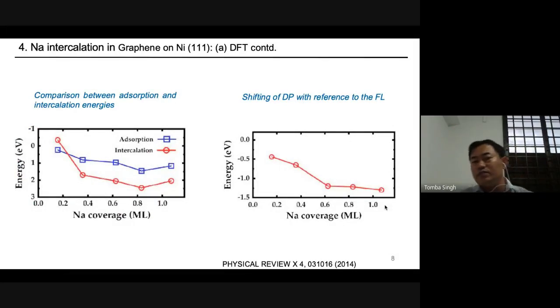So the interaction is much reduced. Definitely, there will be strong competition between adsorption and intercalation. Who will win in this competition? That can be easily understood from the energy analysis versus the sodium coverage. This blue line represents the adsorption, and this red line represents the intercalation. From the energy point of view, the energy is very favorable in the case of intercalation. So if there is competition between adsorption and intercalation, definitely intercalation will take place. So we can ignore the adsorption case.